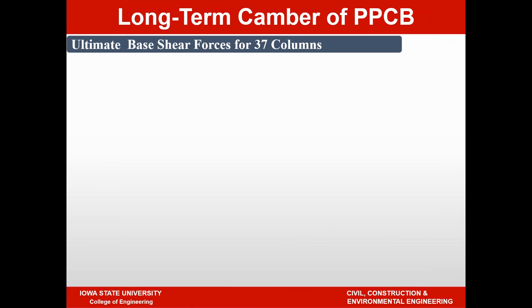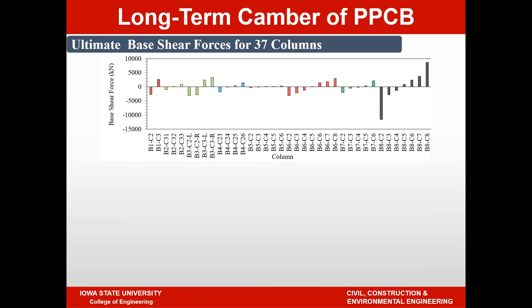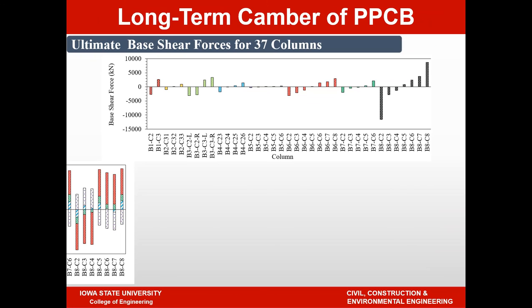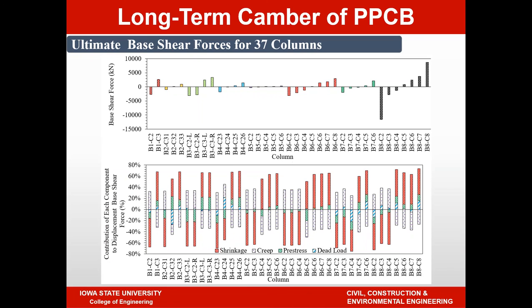If you look at the ultimate base shear, and that's shown here from the analysis for all of the columns, so we have 37 columns from all eight structures. And then this is again showing the percentage of contribution from different time-dependent effects. And again, you can see now that the creep plays a noticeable influence along with the shrinkage strains.